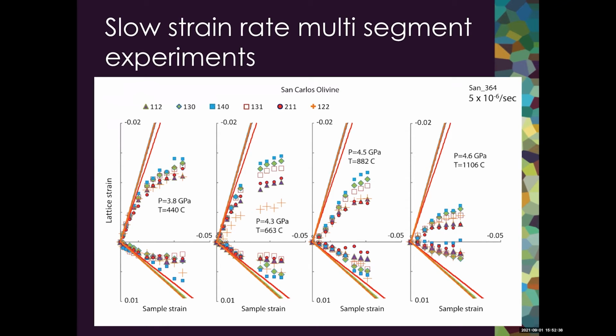And here we have our EPSC model just showing the elastic slope of the aggregate only. And we can see as we increase in temperature, the material is not behaving elastically earlier in the deformation, even in the first strain increment. And so this made it difficult to model the diffraction data. And so we created a slip system used in the EPSC model that would allow us to have a Schmid factor that was the same for all the grains in the early part of the deformation that would allow us to manipulate this elastic slope.